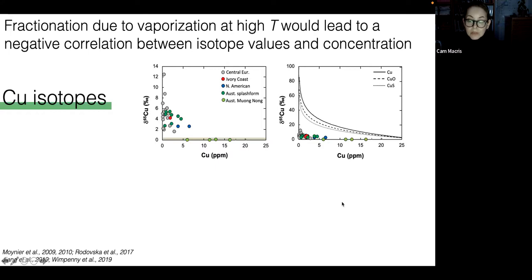Fractionation due to vaporization at high temperatures would lead to a negative correlation between isotope values and concentration, because the light isotopes are preferentially lost from the melt as material is vaporized. In other words, the elemental concentration goes down, and simultaneously the isotope value goes up as the heavier isotopes get concentrated in that depleted residue. For copper, this generally appears to be the case. As copper concentration decreases, moving from left to right here, the delta 65 copper gets higher. This beige bar on the bottom represents the bulk silicate earth, and you'll see that these Muong Nong or layered tektites are unfractionated relative to bulk silicate earth.